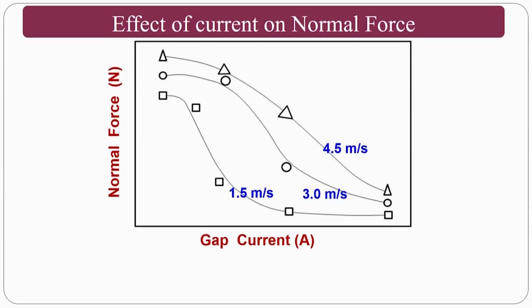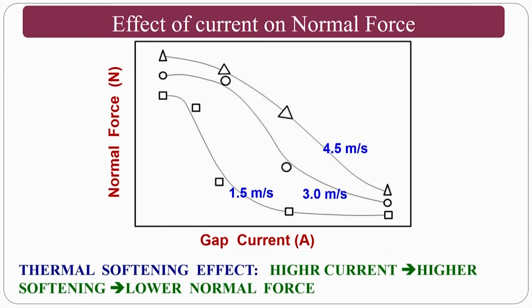So if you see the gap current versus normal force, if you increase the gap current, the thermal softening effect, normally high current, gives higher softening and lower normal forces. That means if you are observing the forces, what is our requirement? Basically transforming from the grinding operation to the electric discharge diamond grinding operation. Our requirement is, if we get a hard material to be machined, assume that I get a workpiece material such as HSS, high speed steel, which is normally considered a tool material for mild steel and other steels in a lathe process. Assume that I want to do the machining on top of it. If you use the normal grinding process, you are going to experience enormous forces.